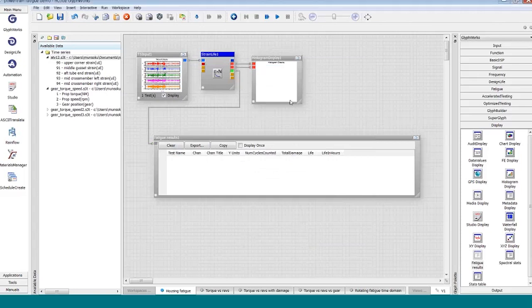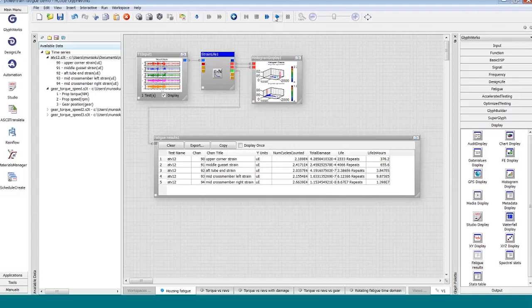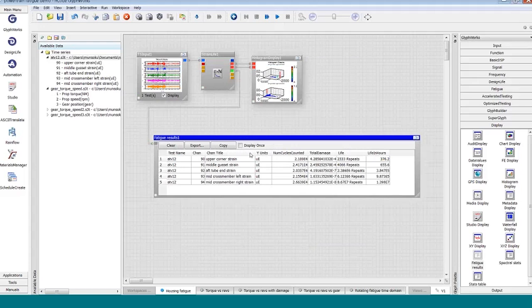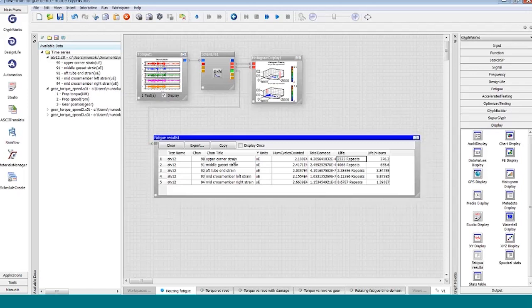Now we can run this process. The strain gauge data is processed and read in to our calculation. Each separate strain gauge has had a rain flow cycle count performed, damage per cycle from the fatigue curve computed, and Miner's rule says damage adds up over time through all those cycles. Here in the middle of the screen we have a display showing we analyzed five channels. On each one, the cycle counting algorithm counted on the order of 2.1 × 10⁴ — about 21,000 cycles. The Miner's damage sum is reported in this display as well. If damage is less than one, it means we can keep on operating until failure.